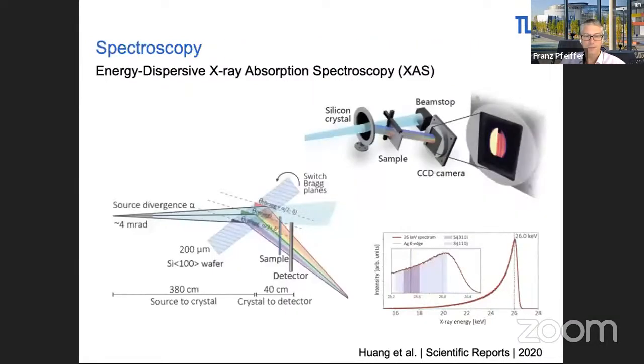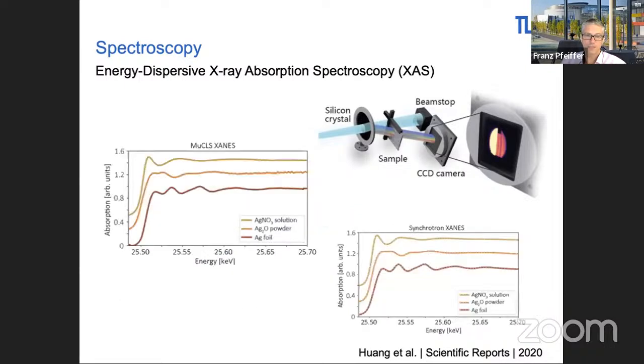Outside of imaging, we've heard also that spectroscopy is requested by many communities. We've also explored that recently by coming up with a halfway clever alignment of silicon crystals and exploiting the natural 4 milliradian divergence of the beam. You can actually do energy dispersive X-ray absorption spectroscopy quite nicely. In our case, of course, in an energy range between 15 and 35 keV, because this is what we have right now. One thing that lies in there is, for example, the silver K edge.